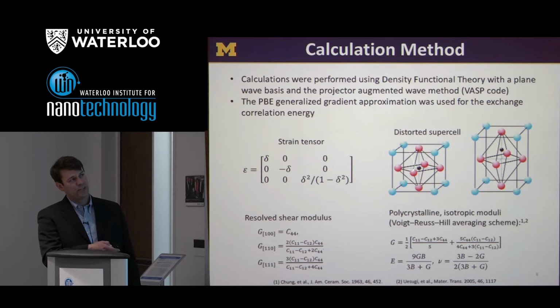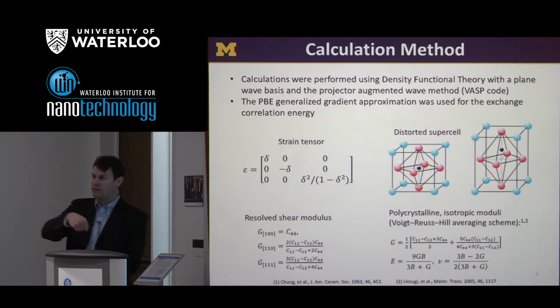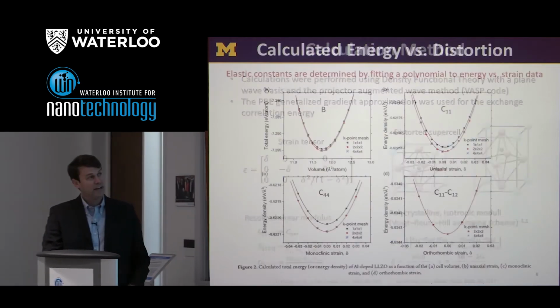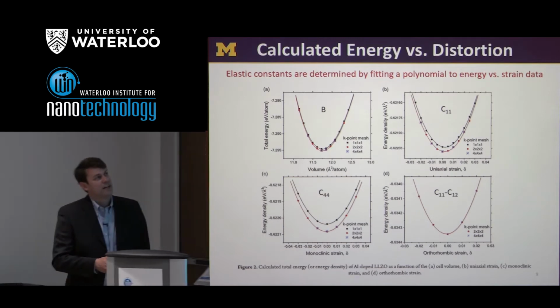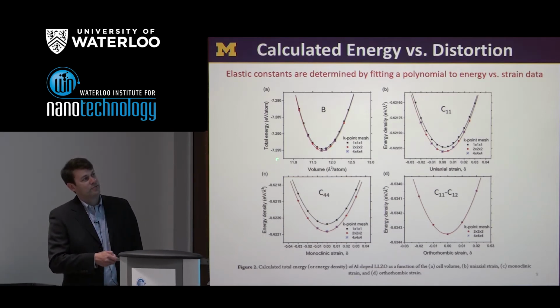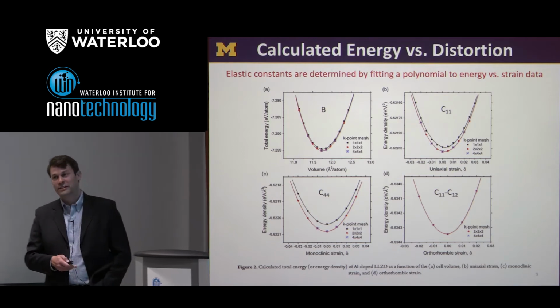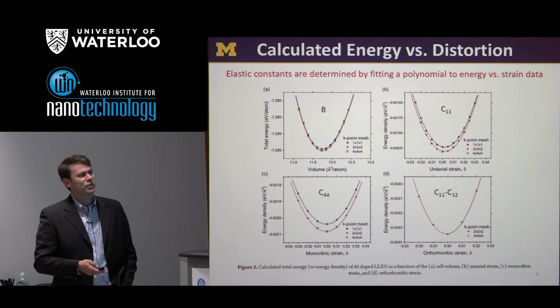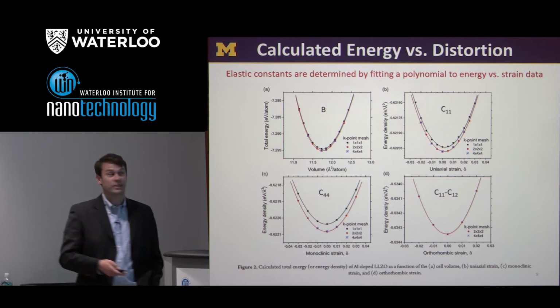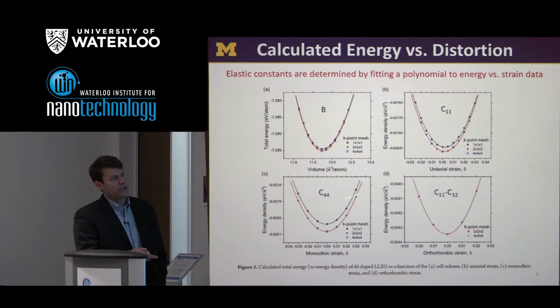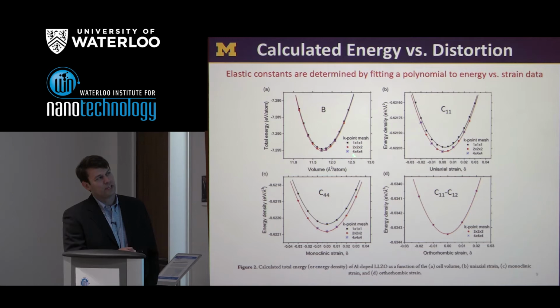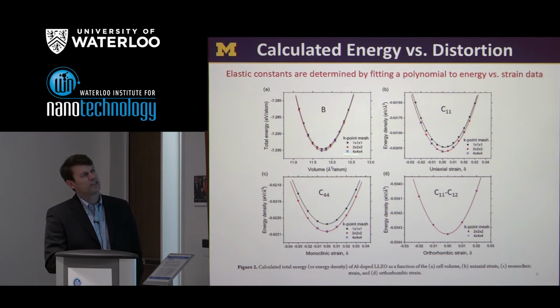So if I had a cubic system, I could, for example, apply a uniaxial strain of different degrees of magnitude, and then I fit the total energy versus strain. In this case, it's a volume strain or a uniaxial strain to a polynomial, and the coefficient of the quadratic term is related to the elastic constant. So you can see there's different curves here. These represent different convergence criteria. Basically, we increase the precision of the calculation until we see convergence in these energies.